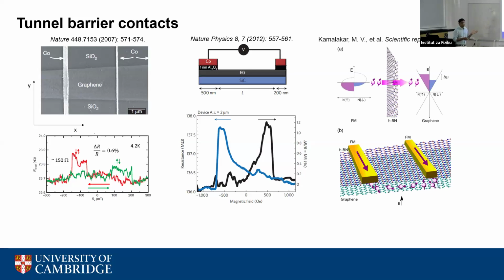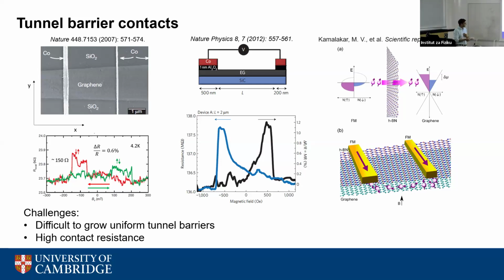Recently, people have kind of given up on growing thin dielectrics because it's really challenging. And what people are saying is that they can use hexagonal boron nitride. Hexagonal boron nitride is an insulator, it is layered, and people insert these insulators between the metal, and they're using these insulators as spin tunneling medium. But again, this is not a scalable approach. You can only make devices by dry transfer in the lab. We wanted to see if there's a way to make these devices at large scale through a compatible method. And here comes our idea of van der Waals contacts, because we want to address this difficulty to grow uniform tunnel barriers of high contact resistance.